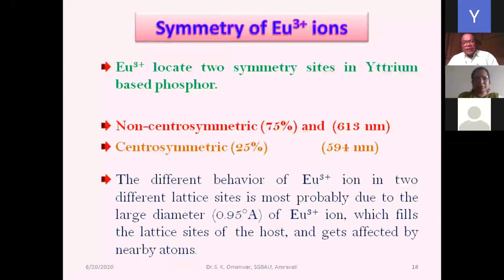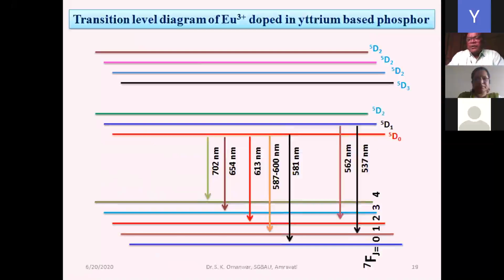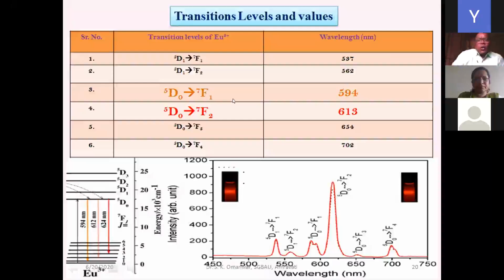The different behavior of Eu3+ ion in two different lattice sites is most probably due to the large diameter, that is 0.95 angstrom unit, of the Eu3+ ion, which fills the lattice sites of the host and gets affected by those nearby atoms. And these are the energy states 5D2, 5D3, 5D1, 5D0, and 7F0, 1, 3, 4. So the transition levels of Eu3+ and the corresponding wavelengths are being given. And this is the dominant, that is 613. So 5D0 to 7F2 is the main transition.